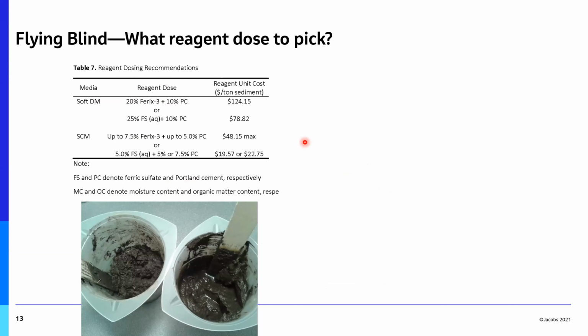All right, so now we said, okay, because our SDM had different characteristics from our semi-consolidated material, we wanted to come up with conservative doses based on those materials and the expected concentrations of arsenic that may be in those. So we selected a dry mix, ferric sulfate source, and the wet mix. But you can see here, depending on what you're going to get in the scow, you have a price between $19 and basically $124 per ton.